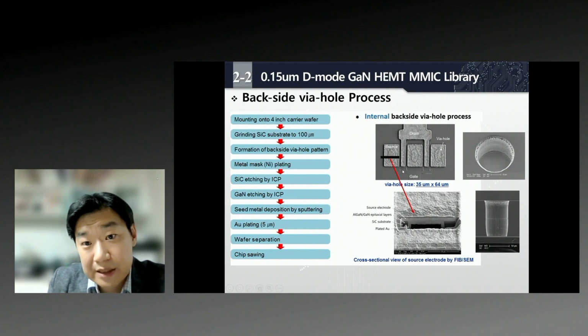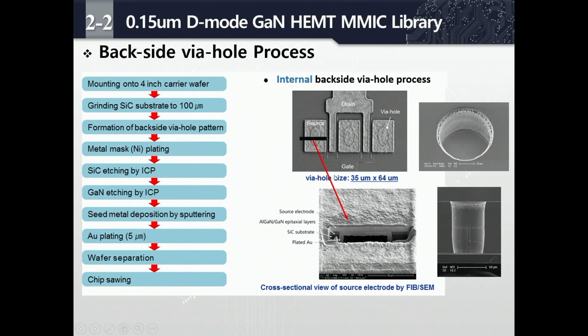This picture shows the backside via hole. Here is a top view of the device. Here are the four gates, this is a source, and this is a drain region. The circle region is a via hole. In the cross-sectional view here, we needed to make a very smooth via hole process. First we needed nickel plating to add a hard mask, and then we etch the silicon carbide selectively by ICP, and then the gallium nitride also by ICP. After that, we needed a 5 micrometer thick gold plating here. And after that, wafer separation, and then finally chip sawing.